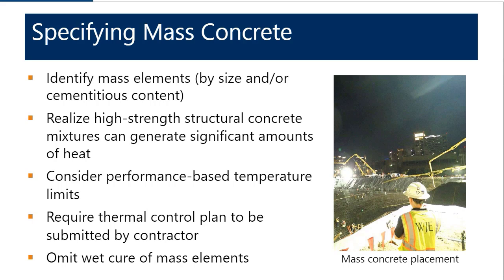One thing to realize is that we're no longer using concrete mixtures with relatively low cementitious contents. As structures are getting larger, spans are getting larger, column spacing is getting larger, we're using higher strength concrete that has more cementitious materials in it. As a result, these high-strength structural concrete mixtures can generate significant amounts of heat, things that we haven't necessarily dealt with 20 or 30 years ago. If you're specifying mass concrete, you should maybe consider allowing the contractor to submit a performance-based temperature limit. In some cases, that can cause the contractor to act in a more efficient way and move the project along in a more timely fashion.